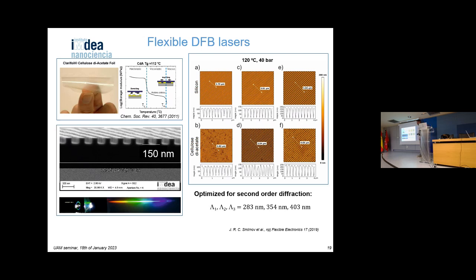Just to show you in more detail how we make some of these substrates: we can either work with rigid substrates, so grooves done on silicon dioxide, for instance, or we can replicate these molds with PDMS and do soft imprinting into cellulose. Either way, you can get grooves with different separation, which diffracts efficiently.